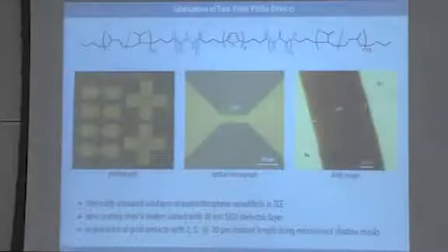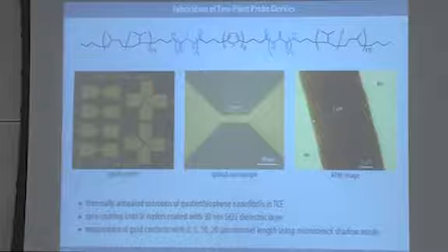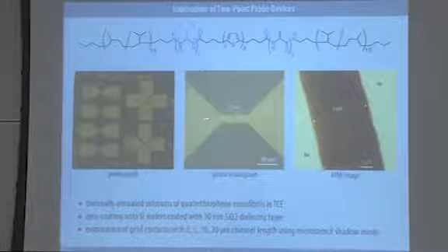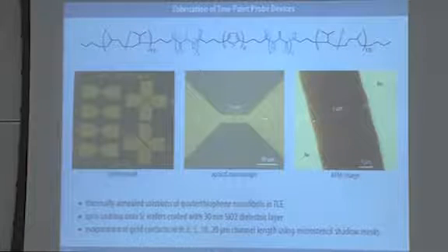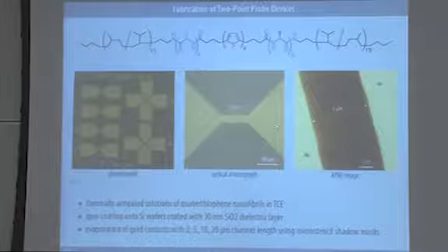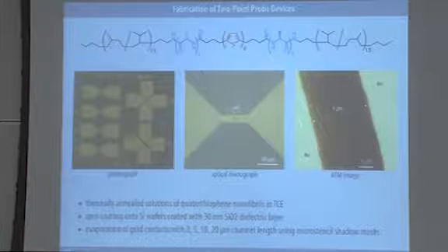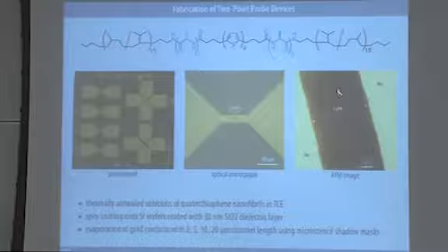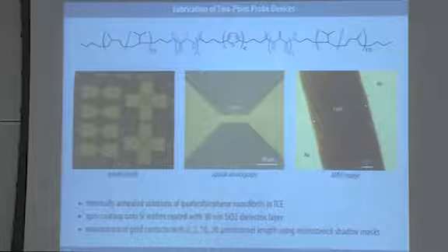So far for charge carrier generation. In the last 5 minutes, I'll quickly show you our results for conductivity of the system. For this, we mainly built 2-point devices where we evaporated gold contacts on top of a very thin film, a sub-monolayer film of our nanofibrils. Here, for example, showing the device with a 5 micrometer channel length.